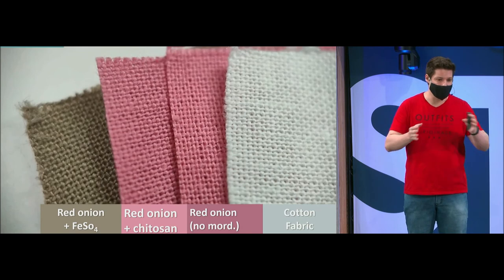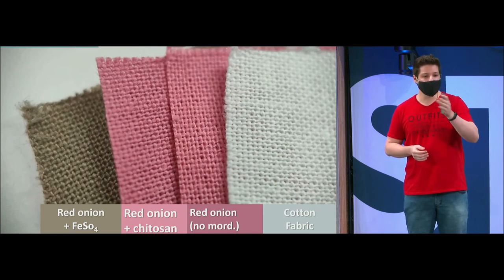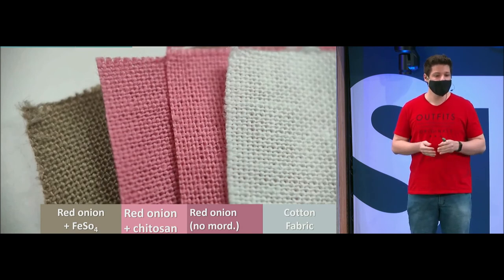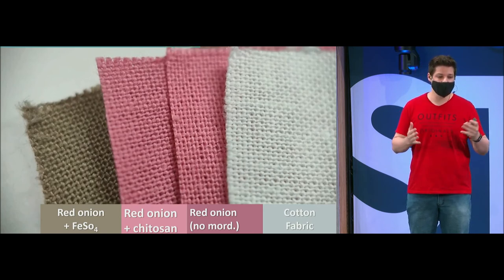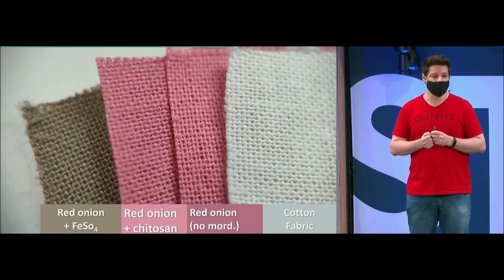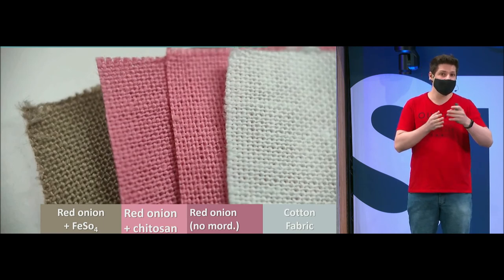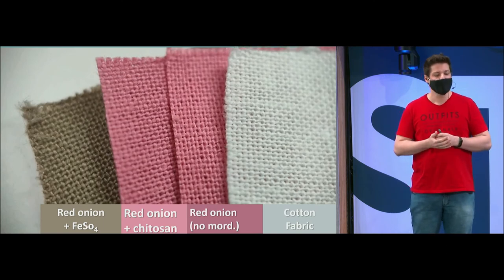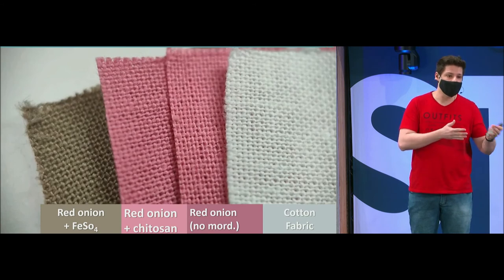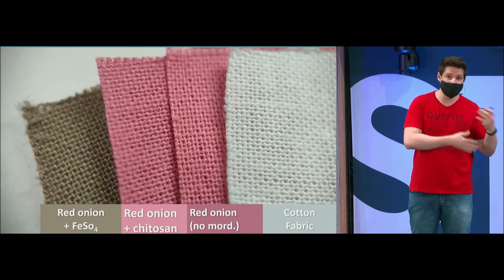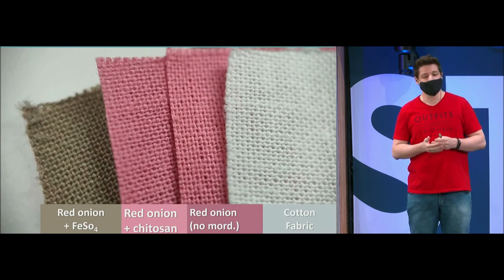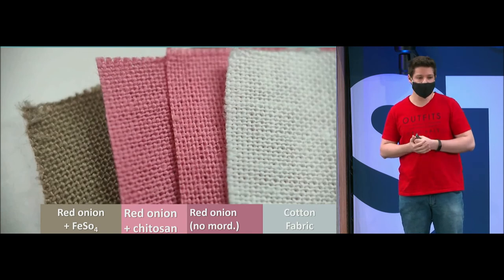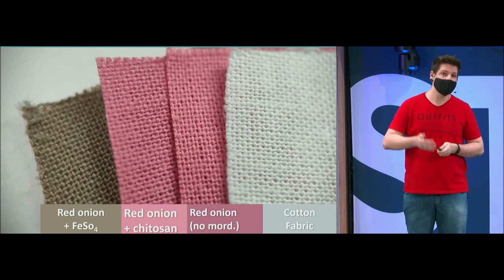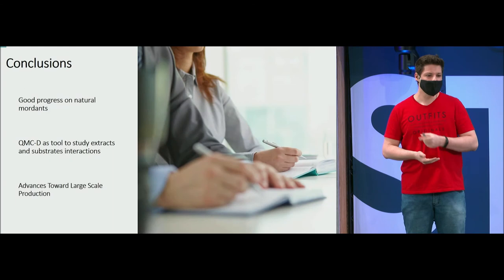So we have some fabrics. The white one is a cotton fabric. And then we have first the red onion without any mordants. We had this nice pink color. And then chitosan helped to keep the same color. And when you use the mordant salts, usually it changes the color of the fabric. So chitosan not only improved the absorption of this material, but also kept the same color.